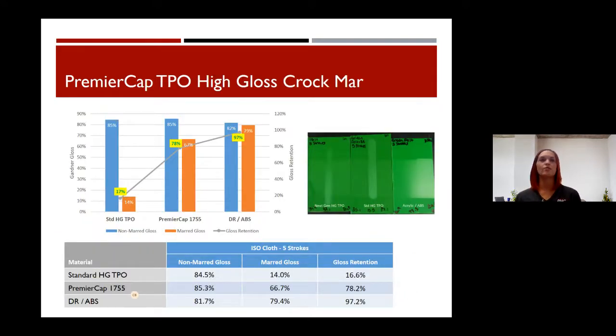Mar, it's basically more of a rub than a point. So it's sort of an abrasion. And it's 5 strokes with a specific type of cloth, and you measure gloss before and after and compare. So again, the acrylic is the gold standard for scratch and mar. You can barely see off to the right that it was ever even rubbed. The standard high gloss, there's a big white streak down the middle. It's pretty obvious, but you can see from the data that the Premier Cap performed very well. Still not quite up to acrylic, but significantly better as far as amount of gloss lost compared to standard high gloss.